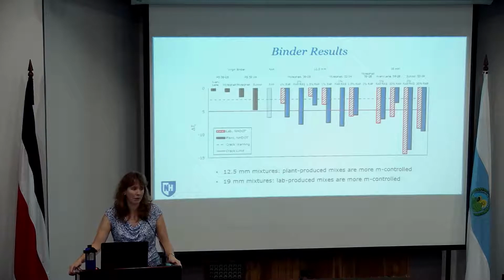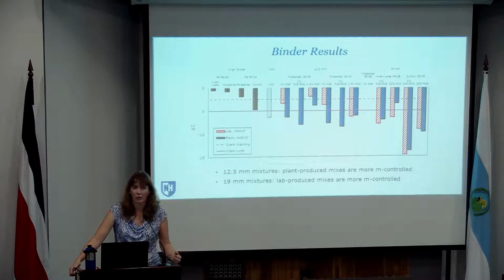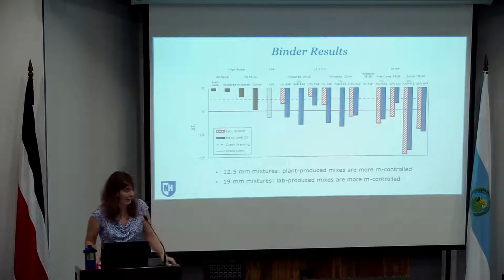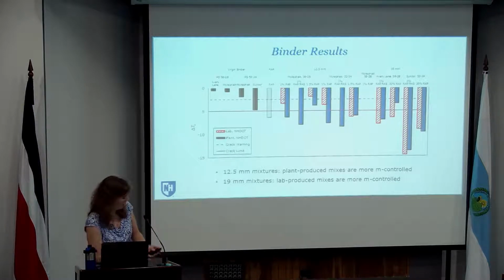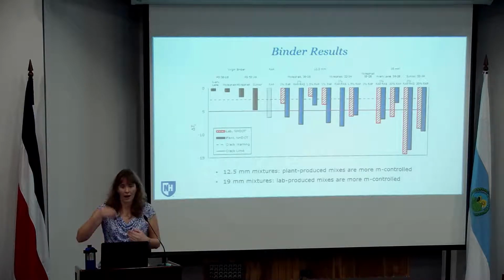So those tend to be materials that you observe relatively early in the life cracking issues with. Okay? And we have seen that in the field as well with some of the field mixtures. Those materials that have been shown to have the REOB at certain percentages did show earlier cracking in the field as compared to other materials. Okay? And again, you can really see it with those Suncor materials, how high those delta TCR values became.